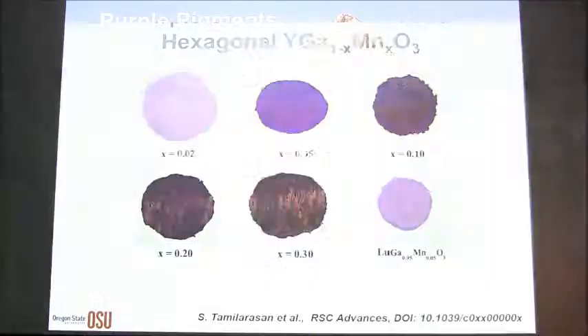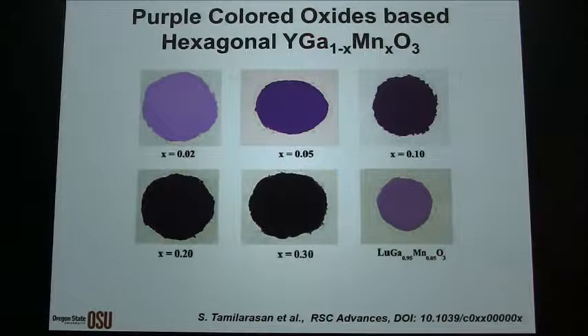So we can also make lavender, purple pigments. Purple pigments are made by using gallium instead of indium. Gallium 1-x, and we put a small amount of manganese in this case. The blue's electronic transition is now changed in such a way that we can shift more towards the red and make it more purple actually. So we can now tune the color of the material by using the structure we know which produces color. So there's a lot of possibilities in this research.